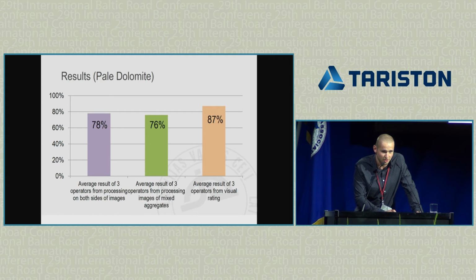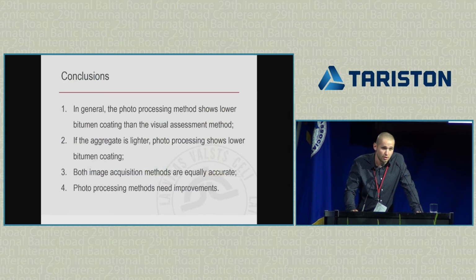So after those 3 specimens, I get some conclusions. The first, in general, the photo processing method shows us a lower bitumen coverage. Is it closer to the truth? I don't actually know. We need to explore it further. If the aggregate is lighter, the photo processing method shows us a lower bitumen coverage. As we saw for the dark granite,